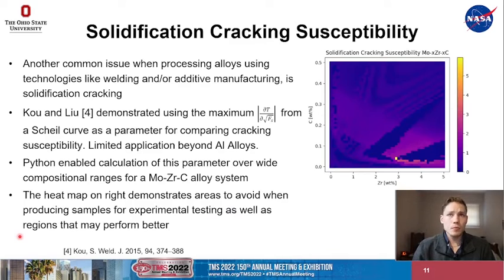Because of this, we moved on to the solidification cracking susceptibility. Another common issue when processing alloys like refractory alloys using common technologies like welding or additive manufacturing is solidification cracking. As I mentioned earlier, Kou and Liu demonstrated using that model, using the maximum of the derivative of the Scheil curve in order to estimate relative solidification cracking susceptibility. They saw good application for aluminum alloys with limited application beyond those alloys.